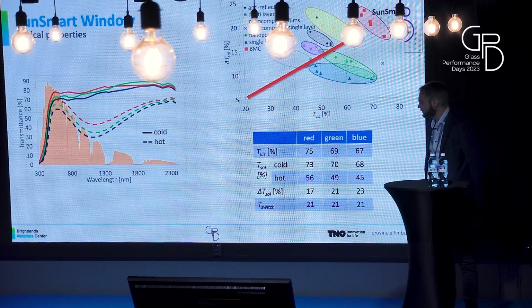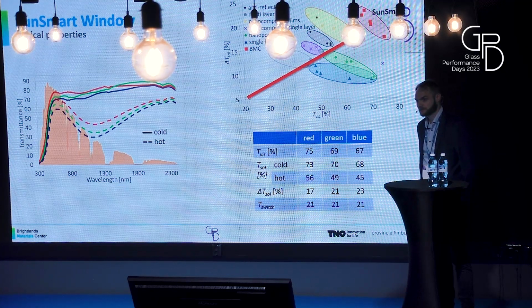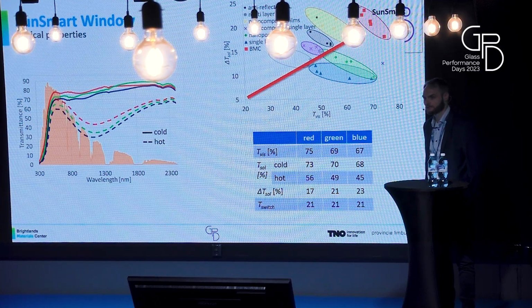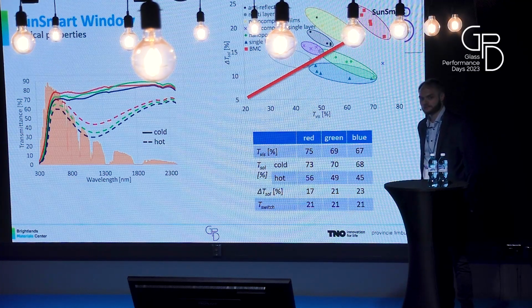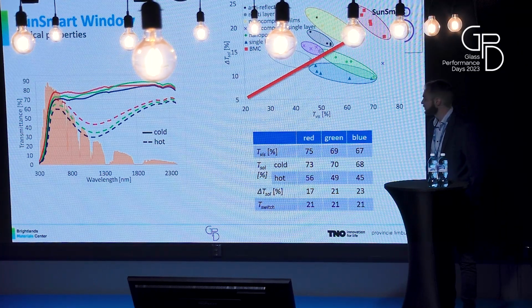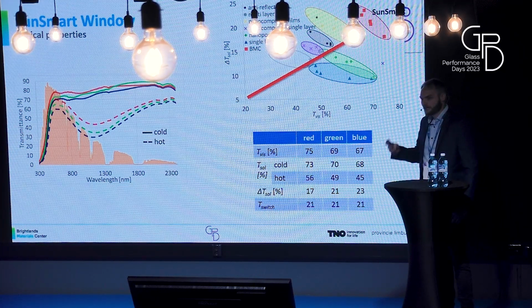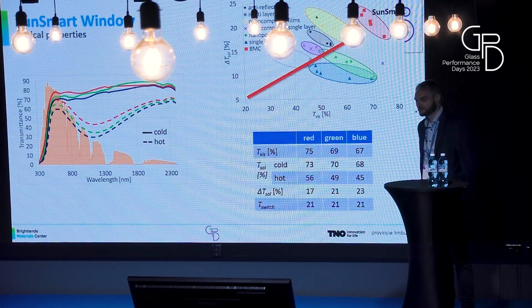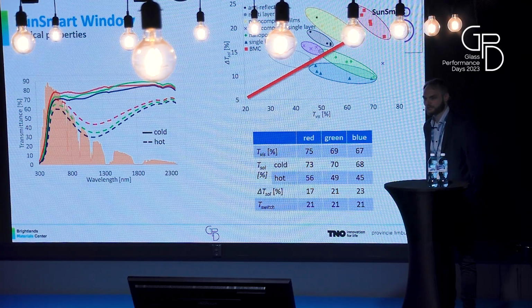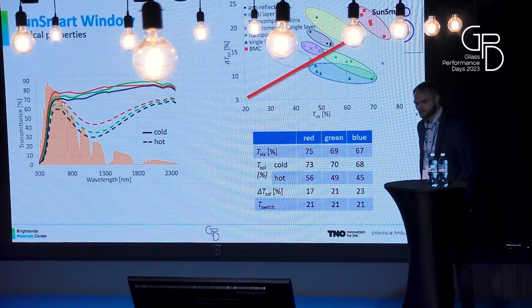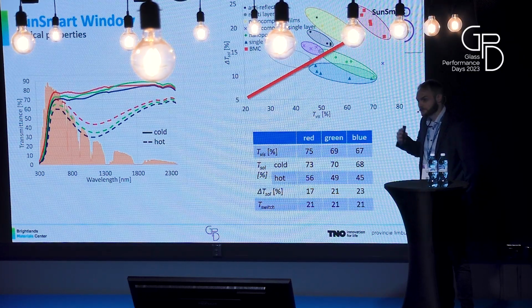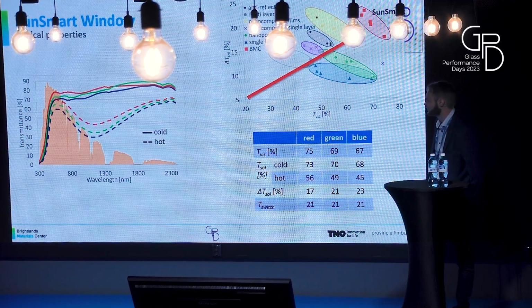That's not only because there the infrared intensity is very high, but also because these coated glass plates, or laminated glass plates, you still need to combine with a low E coated glass, because the material is not impacting the insulation properties of your glass. So you need the insulation of the low E coating to get to your best smart window in the end. And you all know, high-performing low E coatings block a large part of the infrared light. Especially at high wavelength regions, almost everything is blocked by the low E coating. So with the thermochromic material in combination with the low E, you anyway cannot modulate this part anymore.